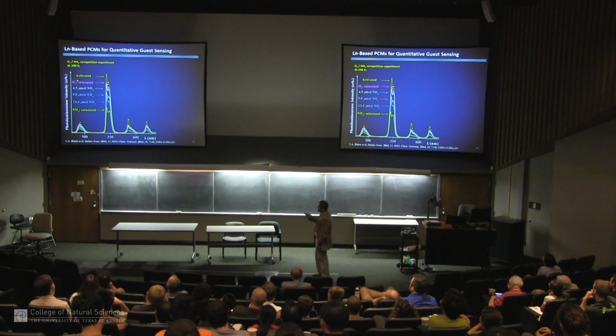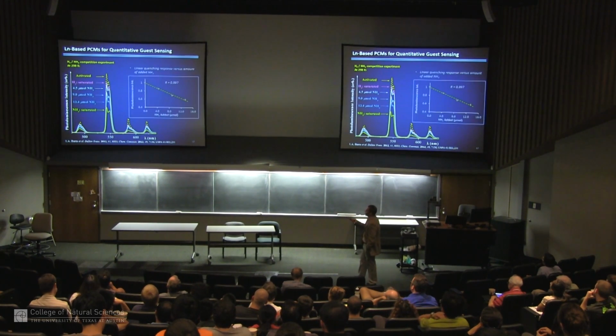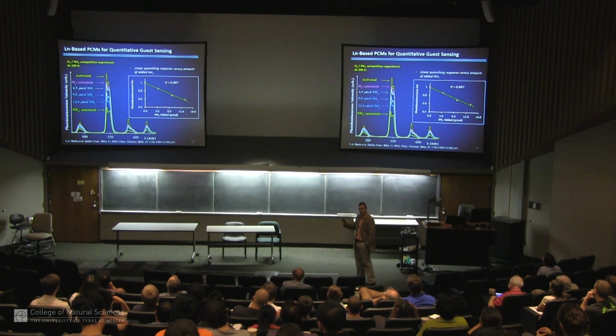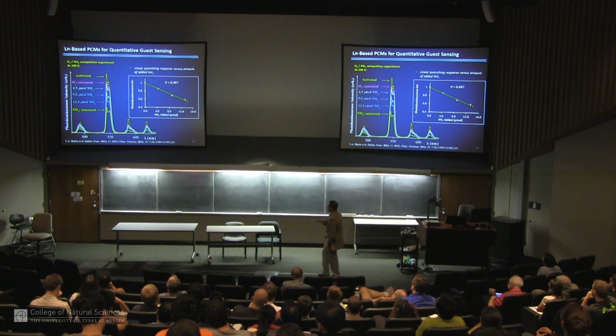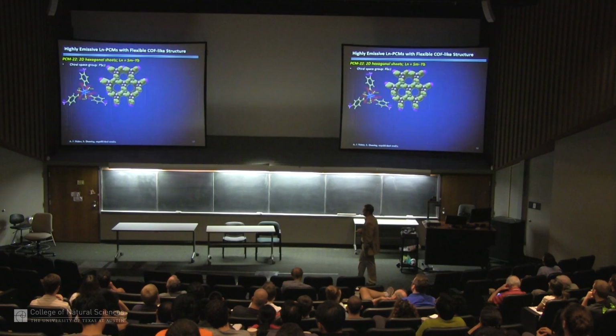And so we can take the material, load the material with hydrogen gas, there's no quenching, start to dose in very small amounts of ammonia to emulate some impurity, and if you integrate the area under the peak, you find this is completely linear, so we can use this as a diagnostic way to back calculate, for example, how much ammonia there is inside the hydrogen gas stream. So this works pretty well for other combinations of gases we've tried as well.